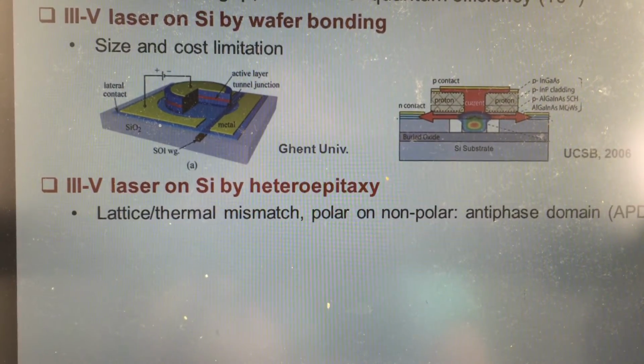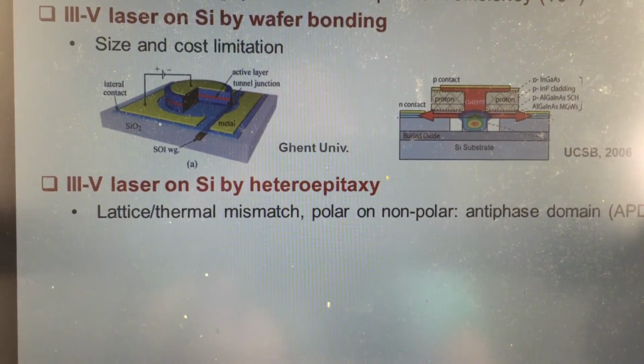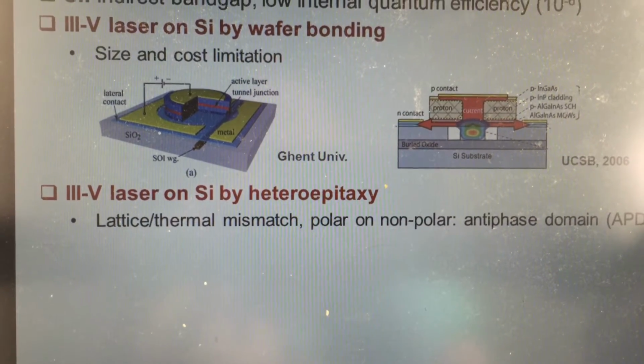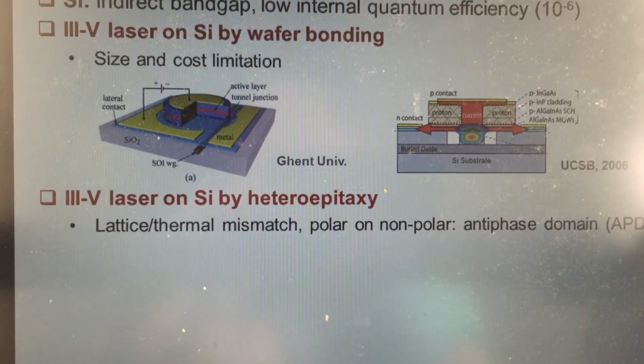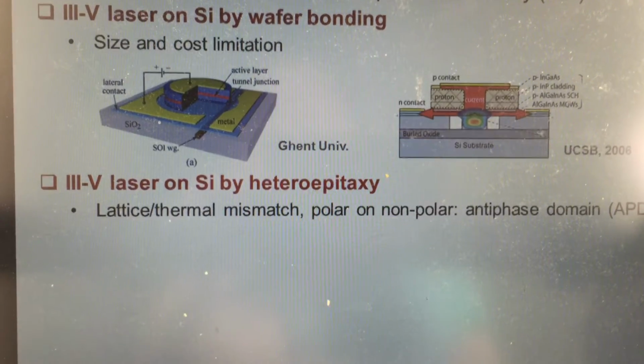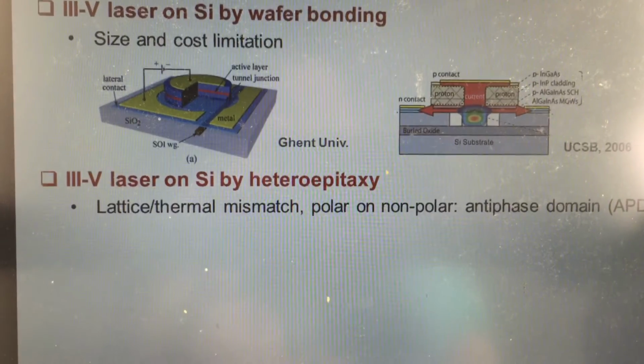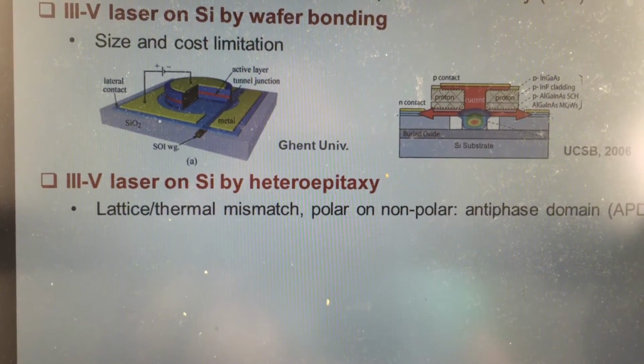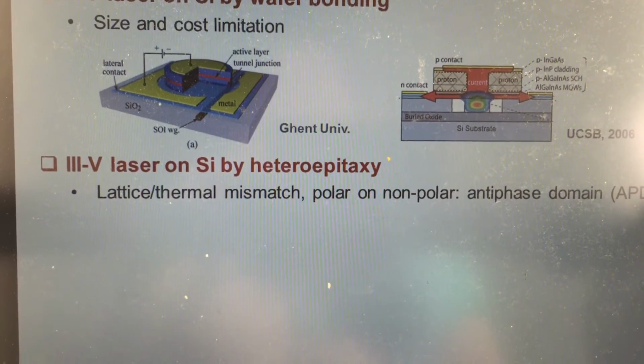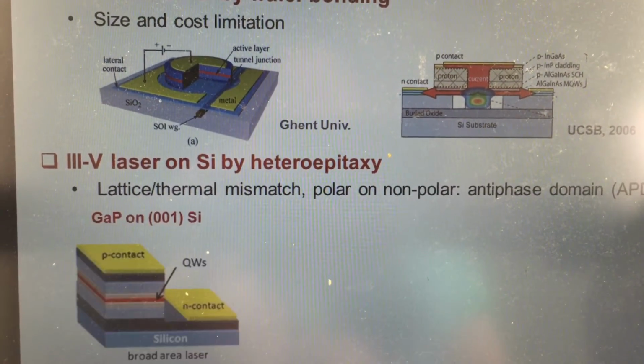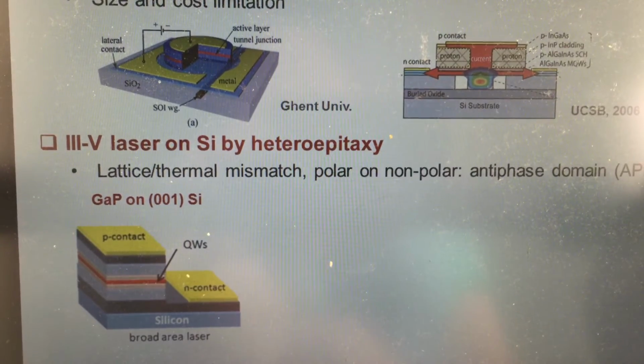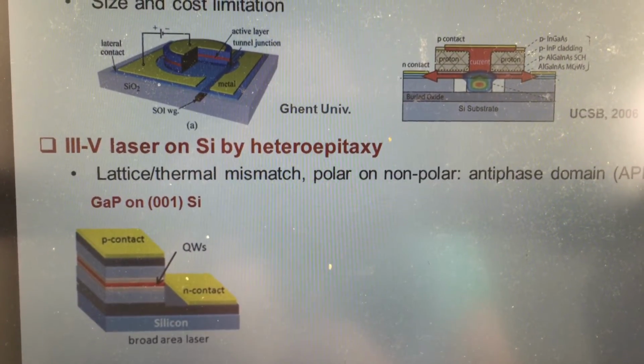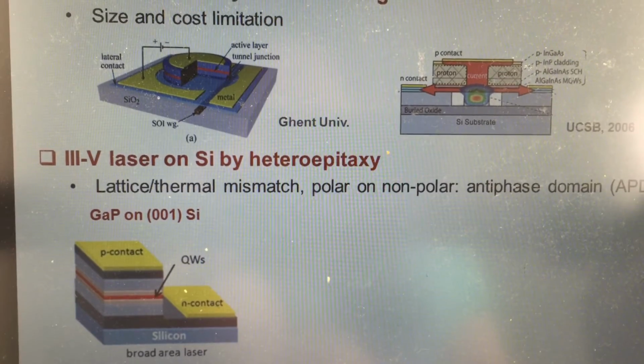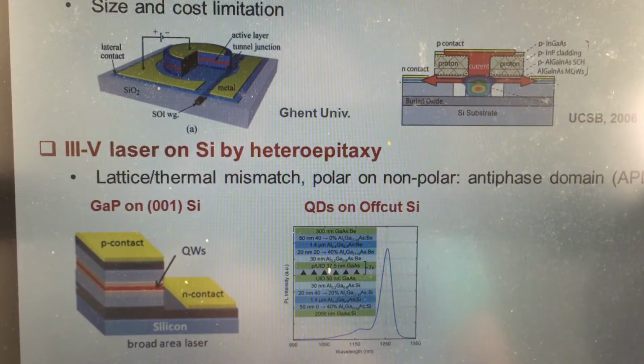However, the growth of III-V on silicon is never trivial because of the very different lattice constant, thermal expansion coefficient, and polarity. The resulted dislocations, stress, and phase domains will degrade the performance and reduce the lifetime of any devices fabricated on the III-V grown layer. There are exciting results with lasers. However, for the gallium phosphide material system, it's challenging to push the wavelengths to the desired telecommunication bands.